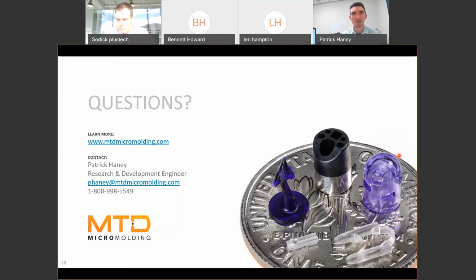So as shear rate increases, the response that it has on the heat generated in the melt is actually exponential, right? So the answer is, although vague, shear heating or shear rates, especially shear rates, can raise the instantaneous melt temperature of your material by a lot. And that's another thing that's actually hard to measure, right? And it's another realm that is really important for studying this kind of stuff.